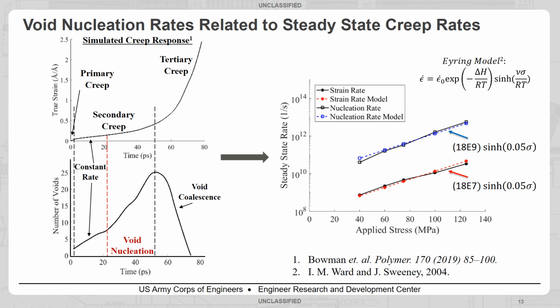So here's some work we've done about 2 years ago on creep in polyethylene using MD simulations. So it's high rate creep, but it was a way to study the creep behavior and how damage develops during creep. So we were able to predict primary, secondary, and tertiary creep here for polyethylene, and then we were also able to count the number of voids that nucleate in the system during that deformation.